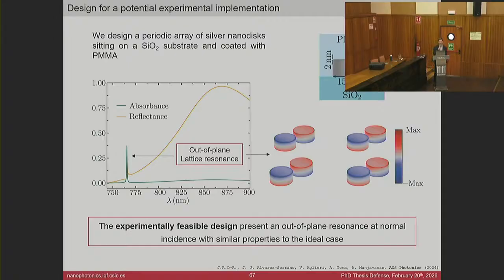Yes, definitely. We have used it in some collaborations with experimentalists, with some systems that were not that easy to model with this semi-analytical coupled dipole model approach. In particular, it was a system in which you had an array of holes, and then some material was deposited inside the holes, such that inside of the holes you had some kind of nanostructures, and at the same time you had a layer of high index dielectric on top. And well, at the end of the day, you can model everything as some higher order multipoles and try to couple them. But at some point, it becomes more useful to just do a full wave simulation, and this is what we did in these cases, for example.